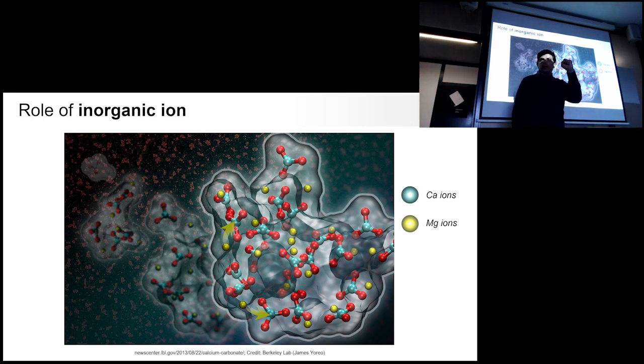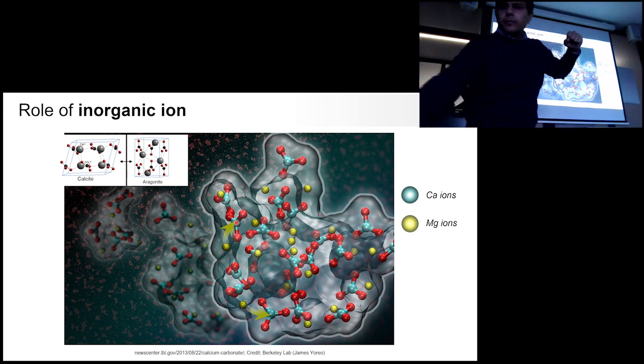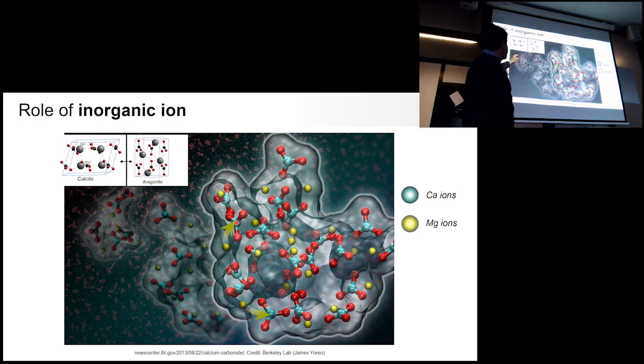But the accepted theory is that magnesium is a smaller atom in comparison to calcium, right? So when you have an excess of magnesium in the solution in which biomineralization is happening, magnesium knocks off some of these calcium ions from their place and takes their place. So then instead of the calcite rhombohedra, you have a change in the shape into an aragonite crystal form.